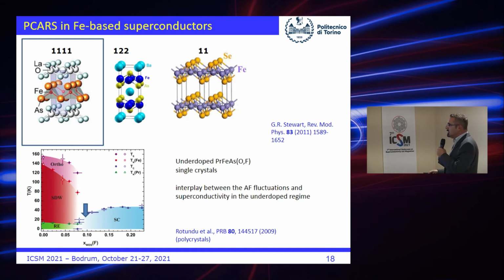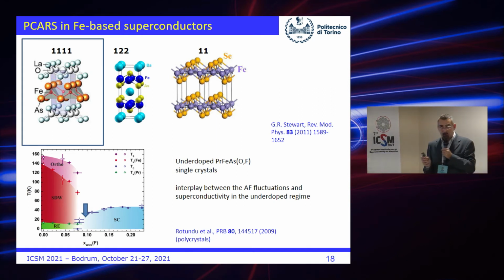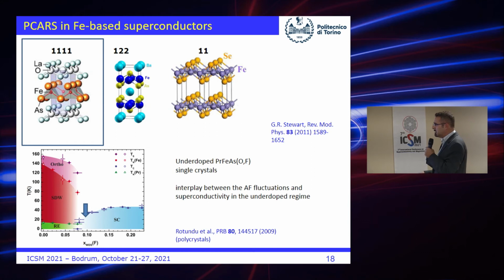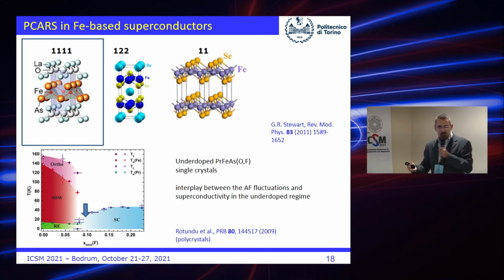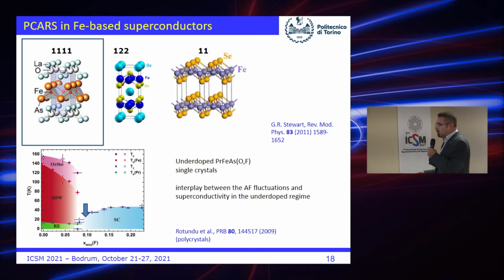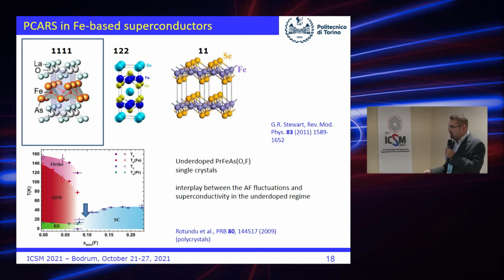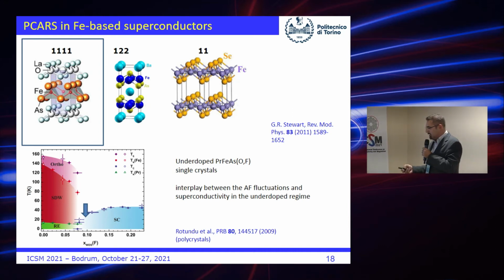Okay, so this is another compound of the same family. This is praseodymium 1111, which is particularly interesting because here you have the spin density wave due to the iron ions, but you also have an ordering at low temperature of the praseodymium ions. So it is particularly interesting to see what happens here. We are already in the region where in principle no long-range order should exist, and in principle, large spin fluctuations should exist because we are very close to this interface.